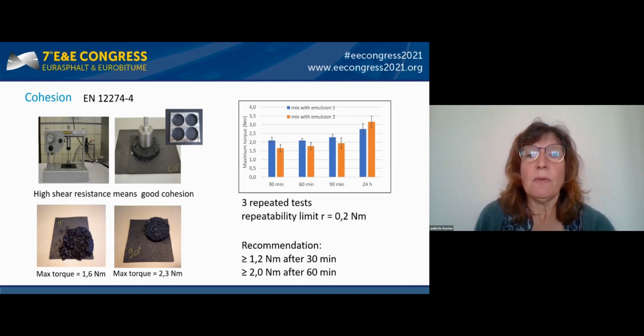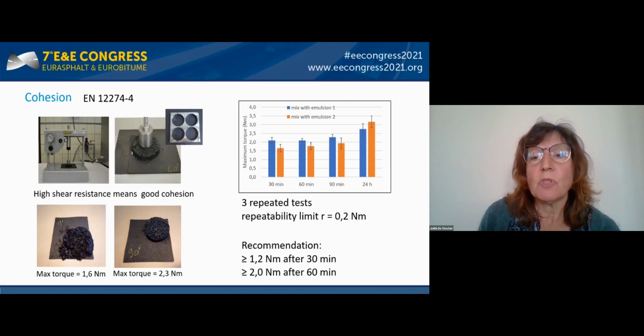This test is also repeated 3 times to get a more reliable average value, and for the average of 3 results, we determined a repeatability limit of 0.2 Newton meter. The test results depend on the emulsion characteristics, but also on the emulsion aggregate pair and on mix composition. And here again, the ESA specifications provided us with adequate thresholds for the typical Belgian slurries that we have tested.